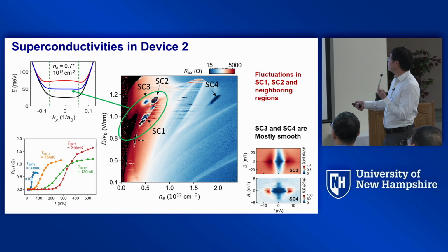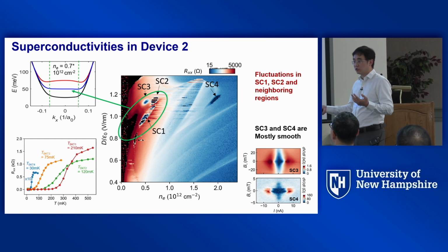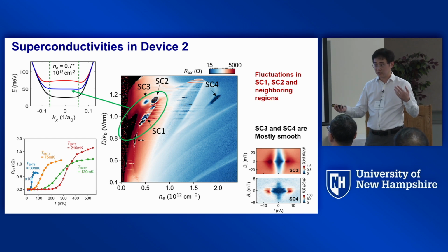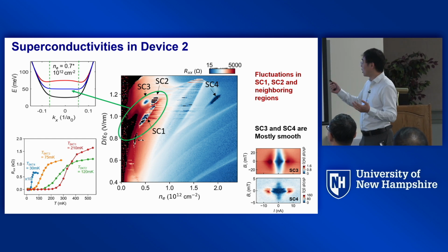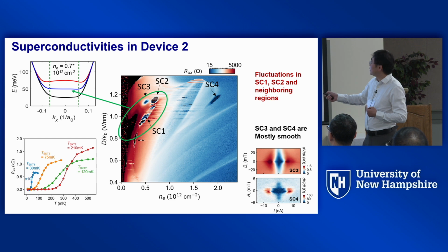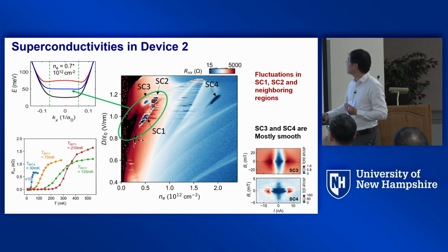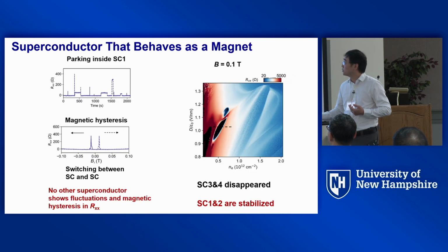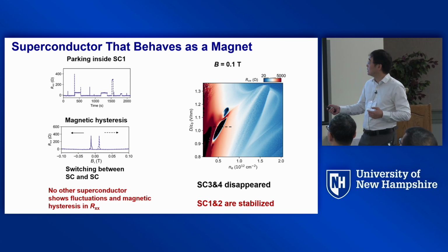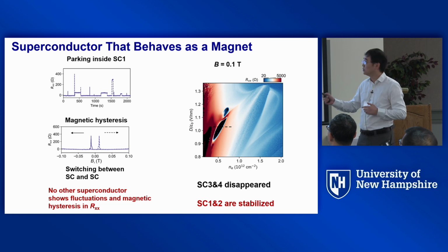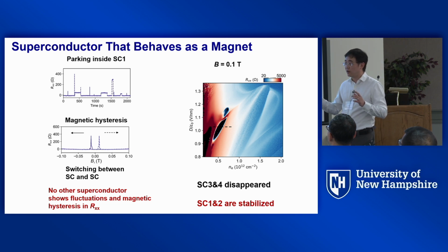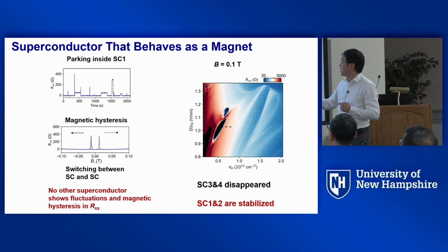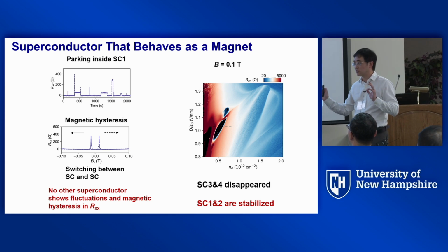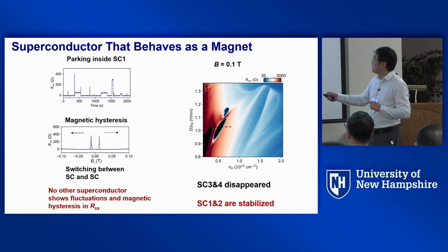If you apply a small out-of-plane magnetic field, you can easily kill SC3 and SC4, which is similar to the superconductivity you get in other graphene systems, say bilayer graphene or trilayer graphene. But SC2 and SC1 are really feeling something is going on. So then we did 2 things. The first thing is that we can park inside SC1. We choose a combination of density and displacement field and just watch it as a function of time. We measure Rxx as a function of time by doing nothing, no scanning of anything, and we got this kind of temporal fluctuation.